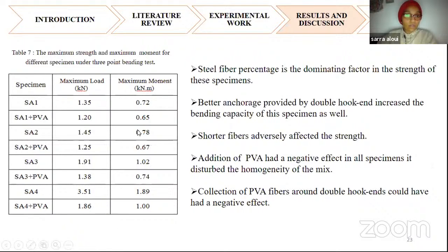Also, if we continue observing this table, we can say that SA3 also has a high maximum load compared to the others. We can say that the better anchorage provided by the double hooked ends increases the bending capacity of this specimen as well. But for the shorter fibers, it can adversely affect the strength. But generally, we can see from this table that the addition of PVA has a negative effect in all specimens. It disturbs the homogeneity of the mix. This is because the fibers collect around the double hooked ends.